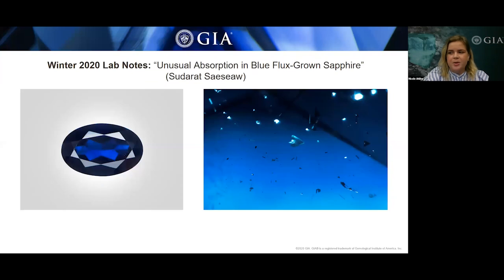The Bangkok Laboratory analyzed a 0.52 carat blue flux sapphire. It had standard gemological properties, including refractive index and specific gravity, that were all consistent with corundum. Microscopic examination of the stone revealed platinum inclusions in a variety of shapes, as you can see in the photomicrograph on the right, which is typical of Chatham laboratory-grown sapphires.